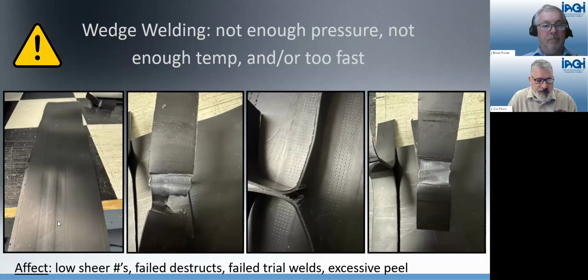The picture on the left illustrates welding too fast, not enough penetration, not enough indentations of the nip rollers. You can see that it's not a good weld. And the other pictures on the right, 1, 2, and 3, are examples of failures. You have low shear numbers, excessive peel, not enough penetration, partial peel, and full peel. So the effect is low shear numbers, failed destructs, failed trial welds, and excessive peel, and obviously costly repairs, which Evan will be talking about in his part of it.